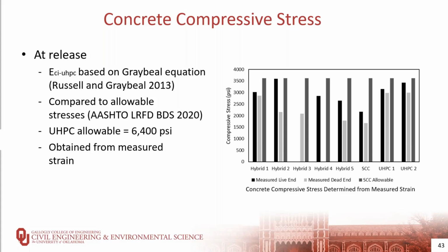However, the UHPC ends exhibited higher compressive stresses than the SCC ends, which indicates that the UHPC pre-stress transfer length is indeed shorter compared to the conventional concrete.